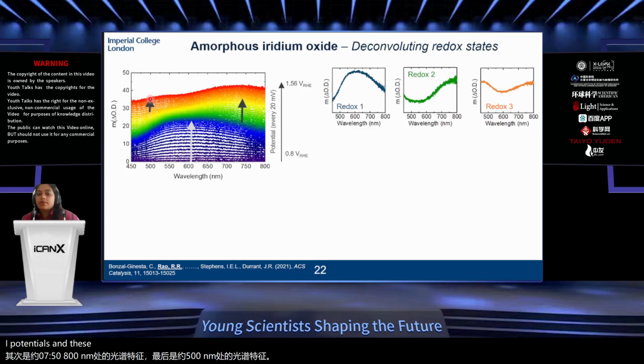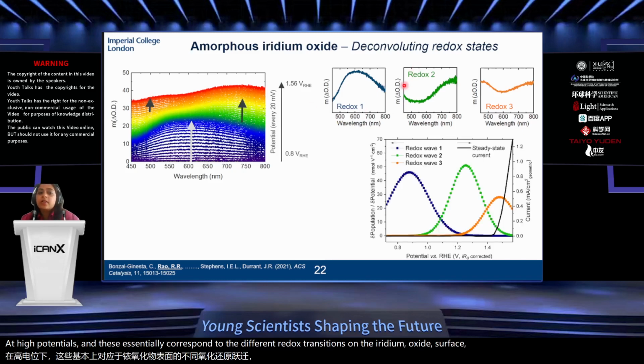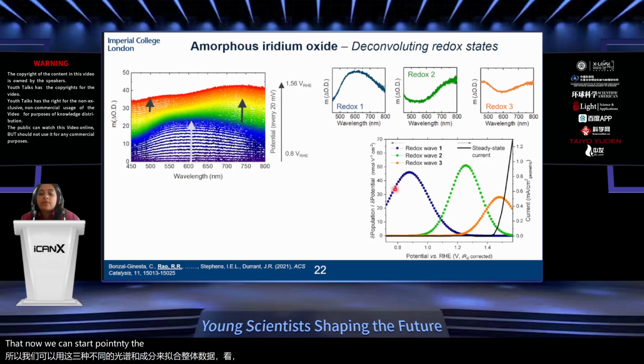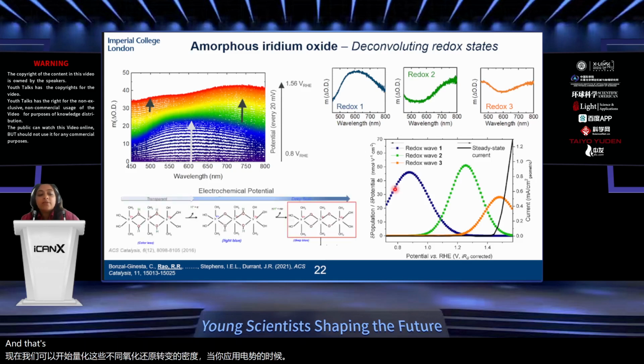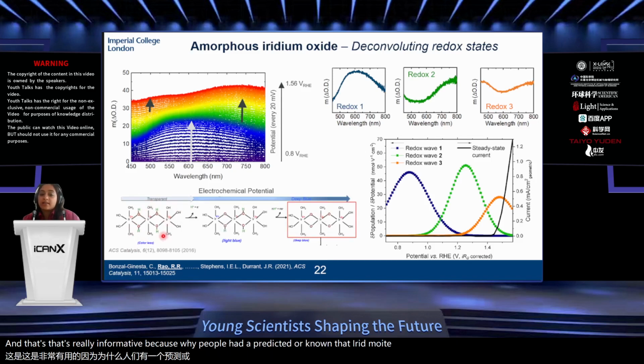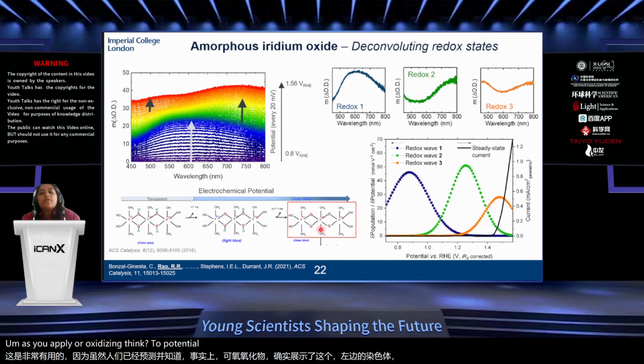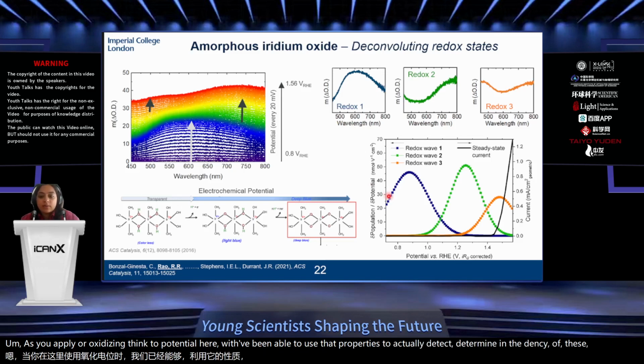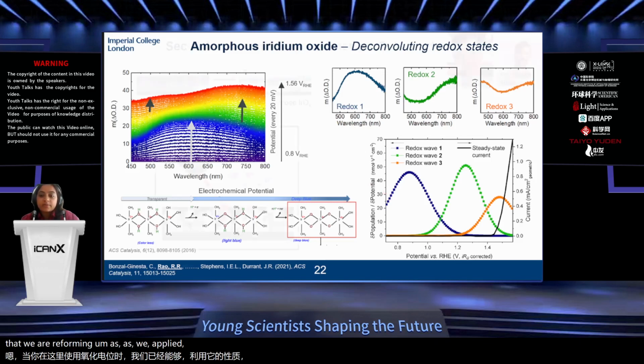And these essentially correspond to the different redox transitions on the iridium oxide surface. So we can go in and fit the overall data with these three different spectral components and see that now we can start to quantify the density of these different redox transitions as you apply potential. And that's really informative because while people had predicted and known that iridium oxide in fact does exhibit this electrochromism as you apply oxidizing potentials, here we've been able to use that property to actually determine the density of these species that we are forming as we apply potential.